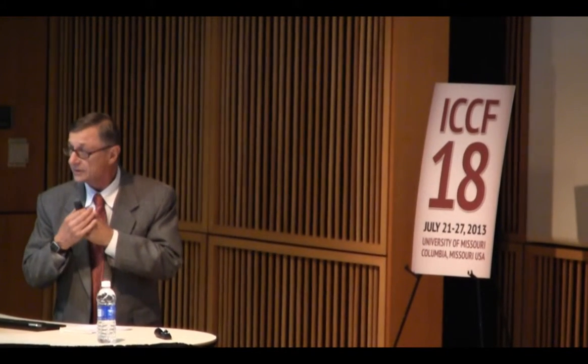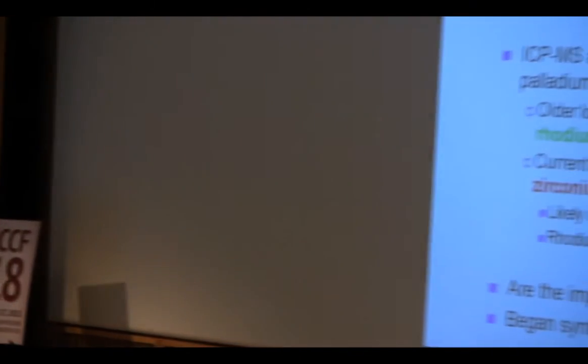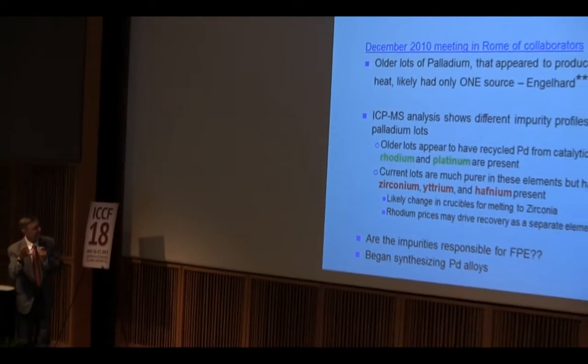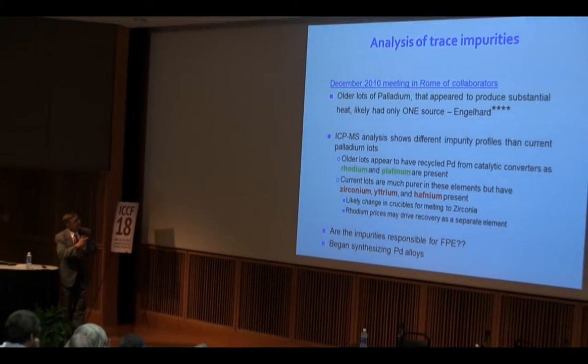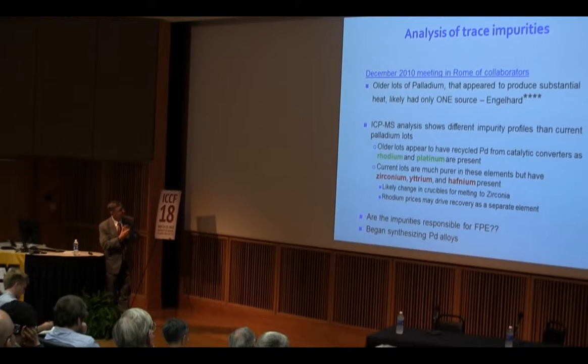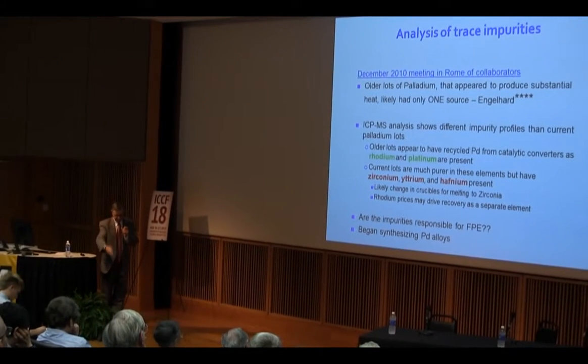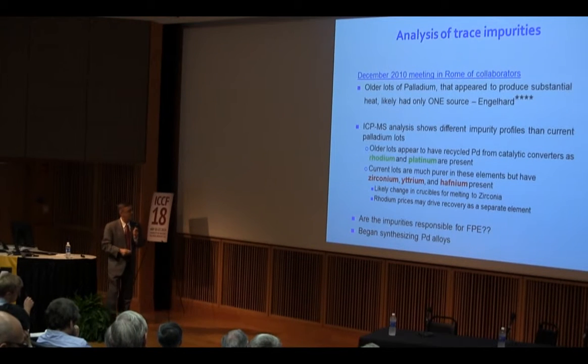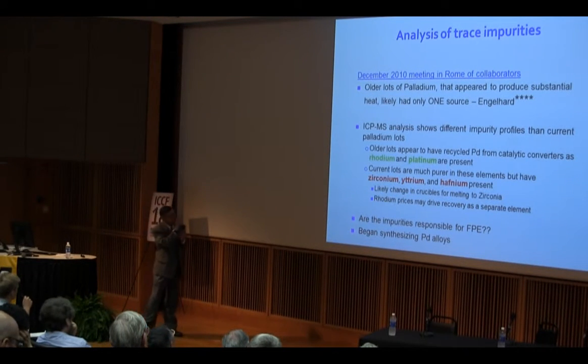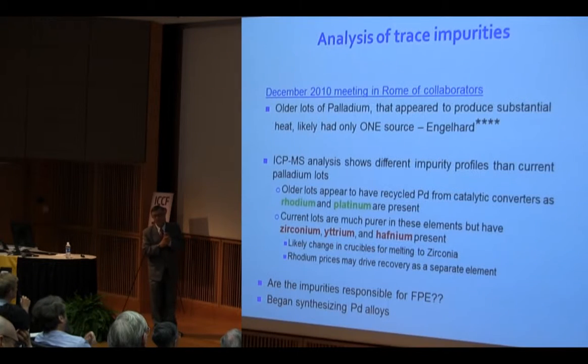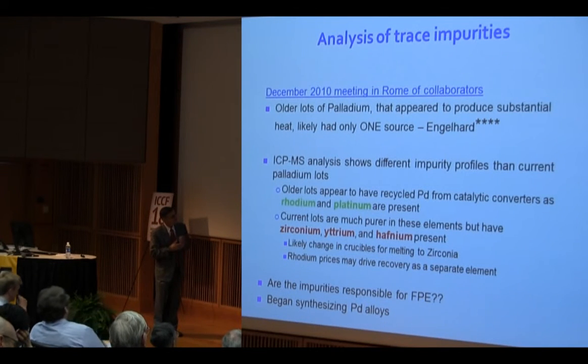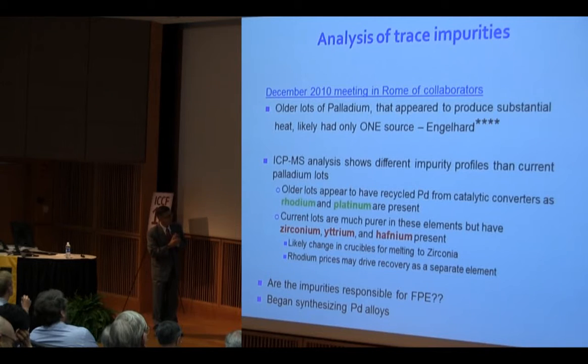Now this view graph that David showed, and I have to get to the tutorial because I don't quite agree with what the impurities were in his lots, and I think this refers to the older lots, and he was not referring to the older lots. But it was realized right around 2010 at ENEA when Mike and David Knies and Victoria were going over data that the older lots had rhodium and platinum in them, about 50 parts per million rhodium, up to 200 parts per million platinum. And the newer lots had zirconium, yttrium, and hafnium. That's where the zirconium is. All of these pin grain boundaries.